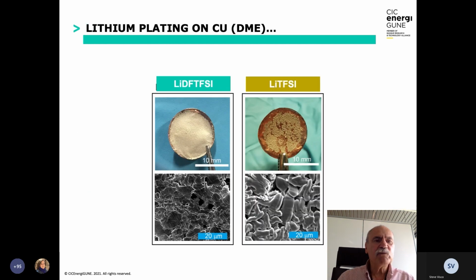And effectively, if you plate lithium onto copper using DME because you want to be able to see this lithium, as you can see with LiTFSI, it is quite dendritic and discolored, and you can see the porosity of the dendrite. And if you plate lithium from DF-TFSI, you can see a shiny, smooth membrane of lithium which has been deposited. And so the SEI that this salt gives is far preferable to that obtained with conventional LiTFSI.